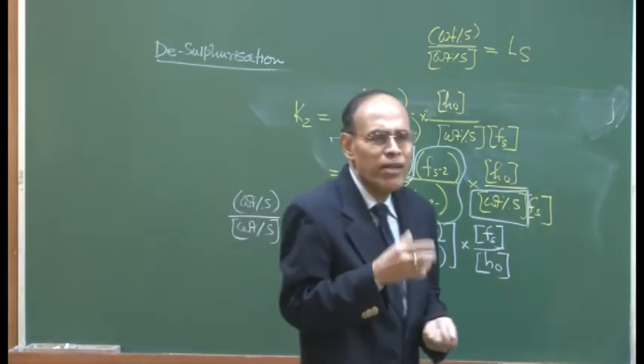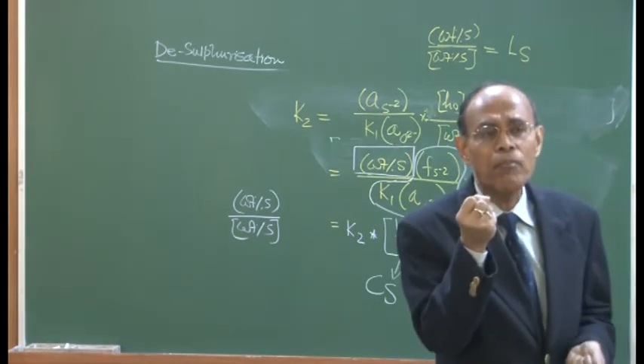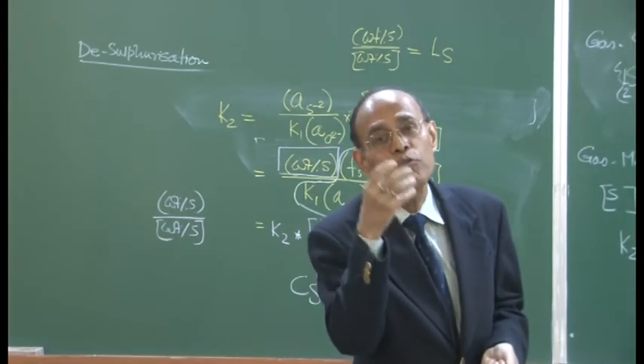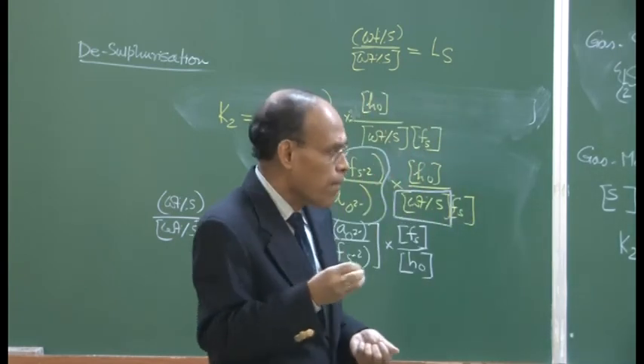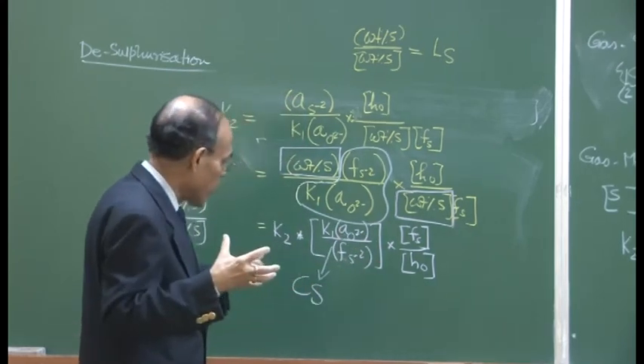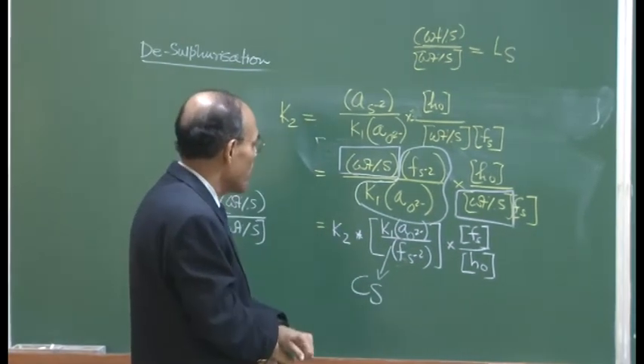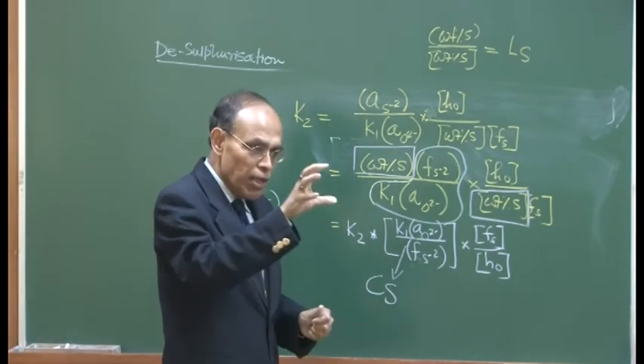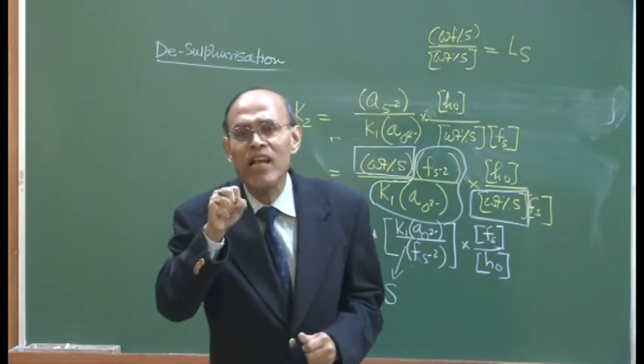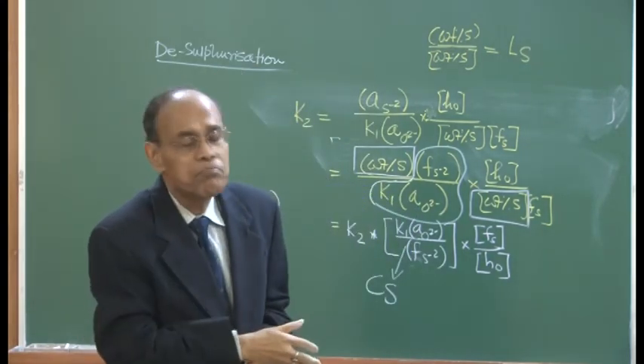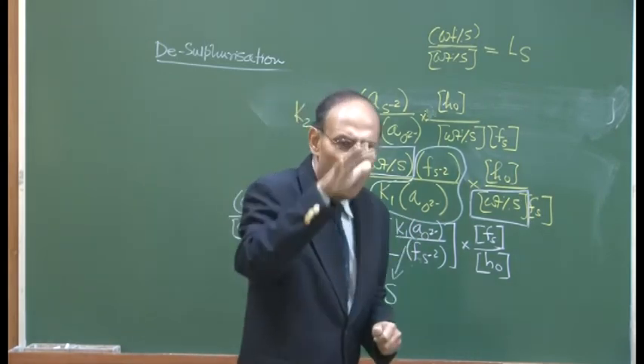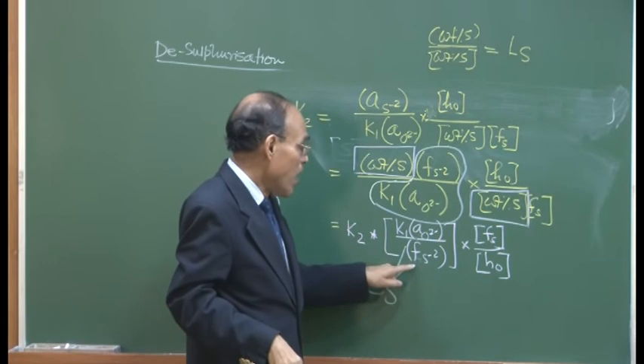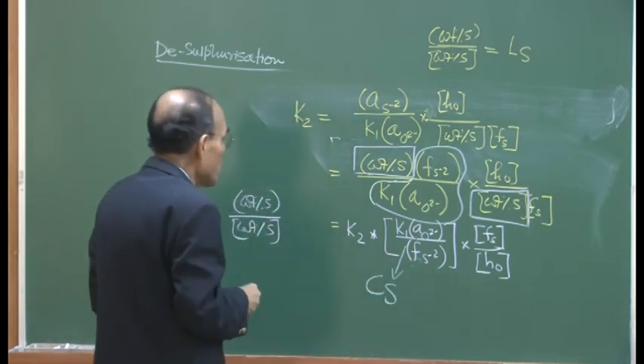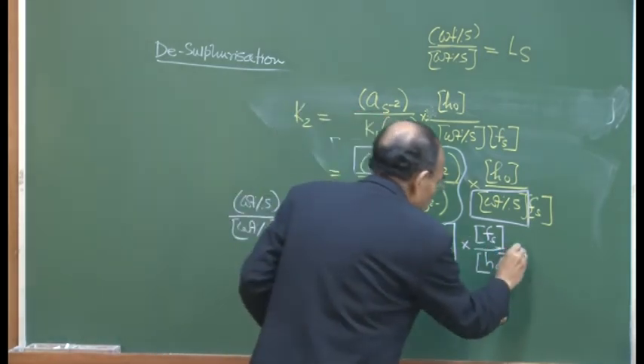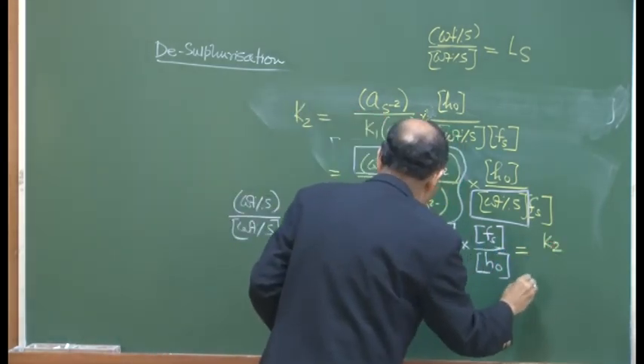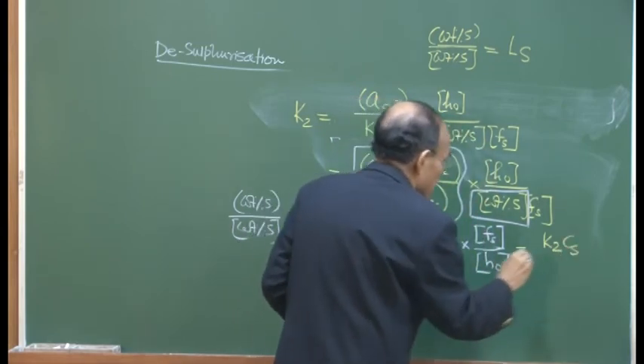You must understand that if you have a very stable phase, in that case the activity coefficient is going to be extremely small. On the other hand, if you have something which is very loose, not tied up very strongly, in that case the activity coefficient is going to be very, very large. So if lime can fix sulfur as calcium sulfide, sulfur will exhibit a very low activity coefficient. On the other hand, the smaller is the content of lime in the slag, the higher is going to be the activity coefficient itself. So therefore, we can say that the final expression is K2 into CS, sulfide capacity, into FS